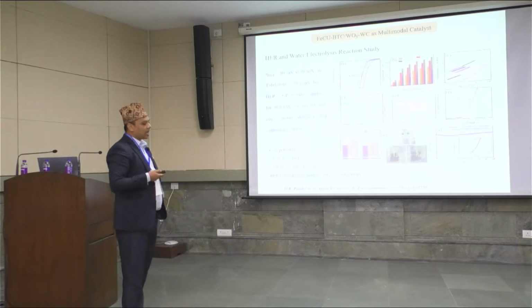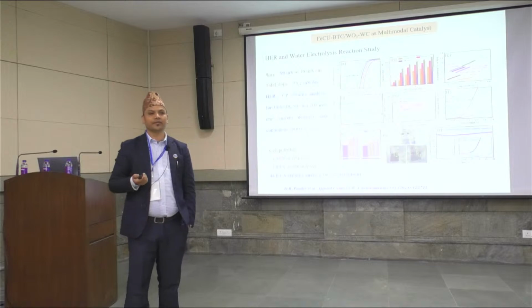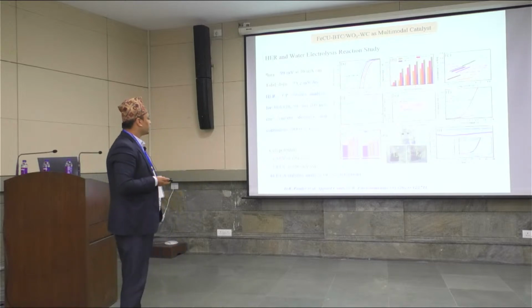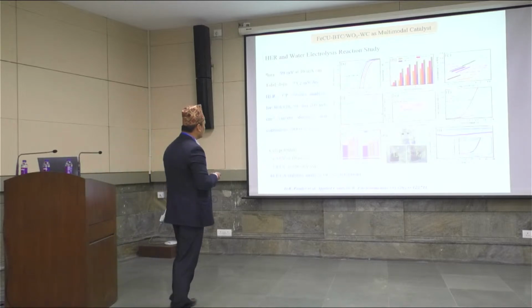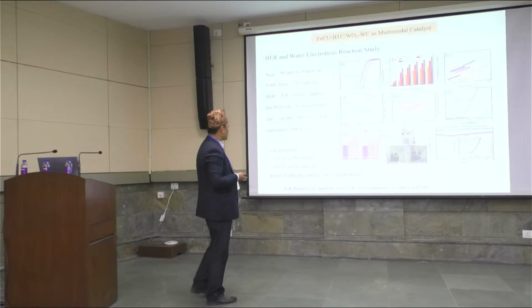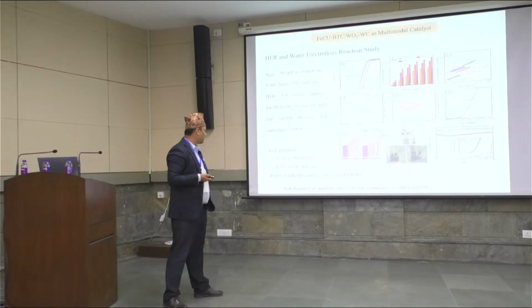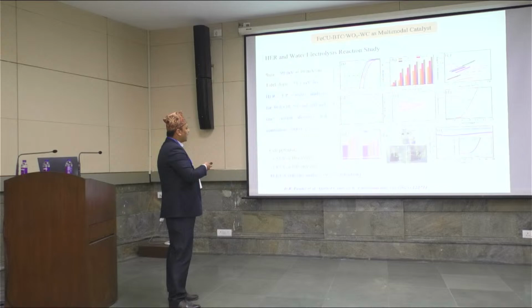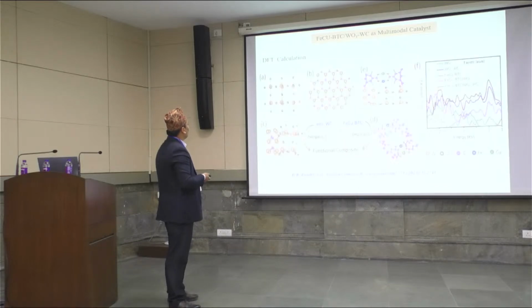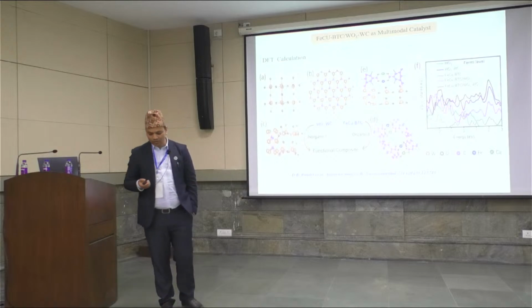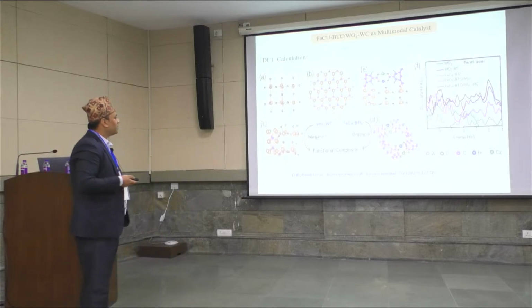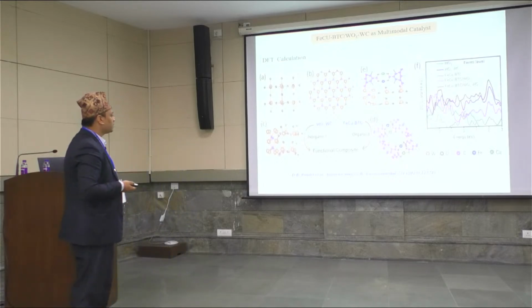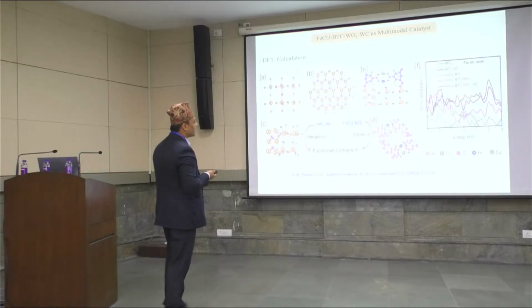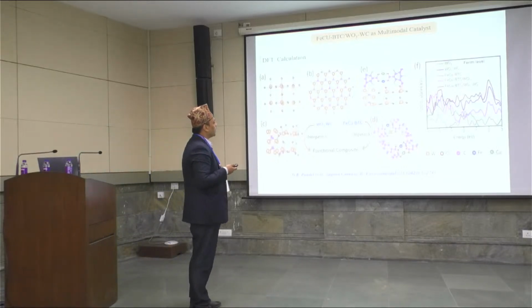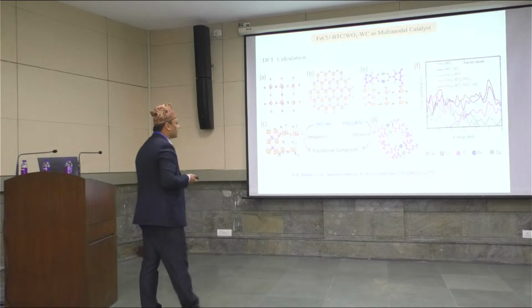And this is the hydrogen evolution reaction and the cell setup for the water electrolyzer. We set up the cell for the water electrolysis reaction where the cell potential is around 1.53 at 10 and 1.83 at 100 milliampere per cm square. And this is the stability for 48 hours of CA. We did a very small DFT calculation, and here the density of states is calculated, where our composite catalyst shows a very good total density of states at the Fermi level.